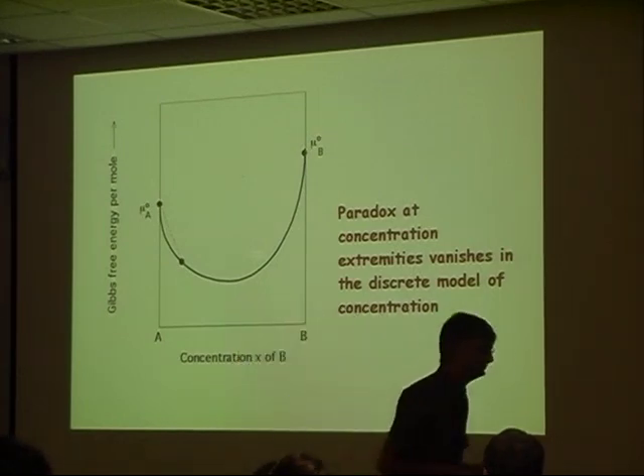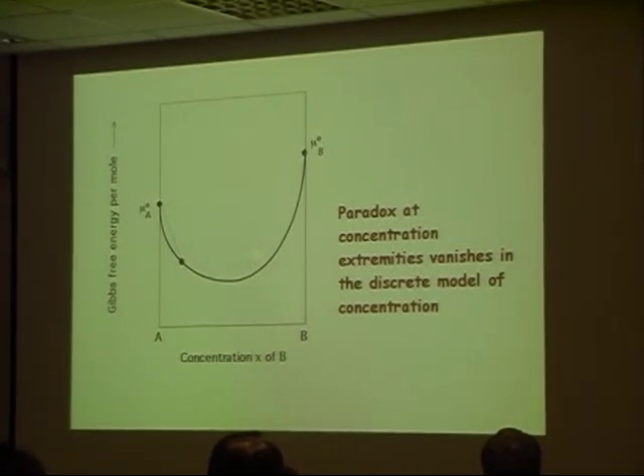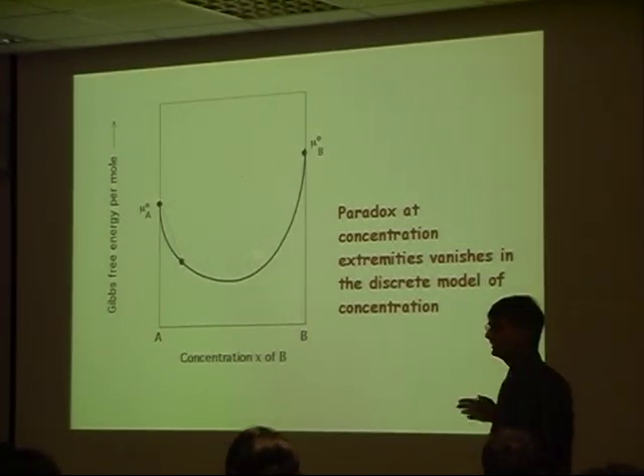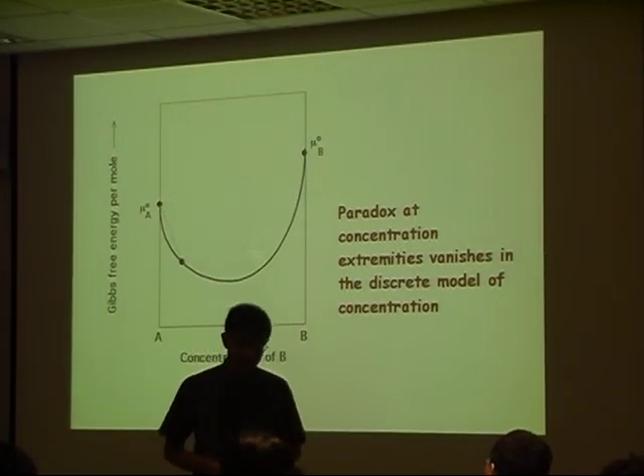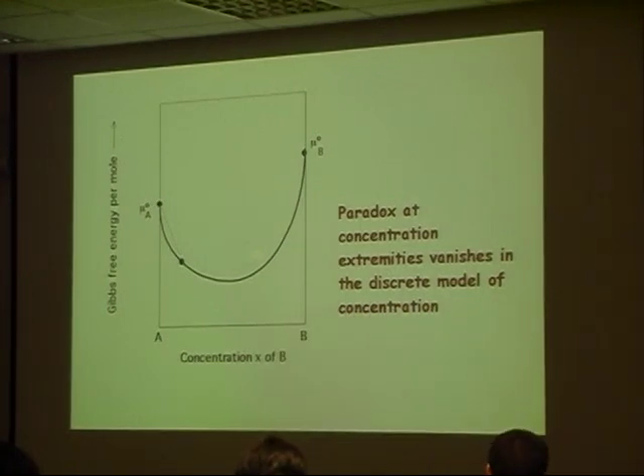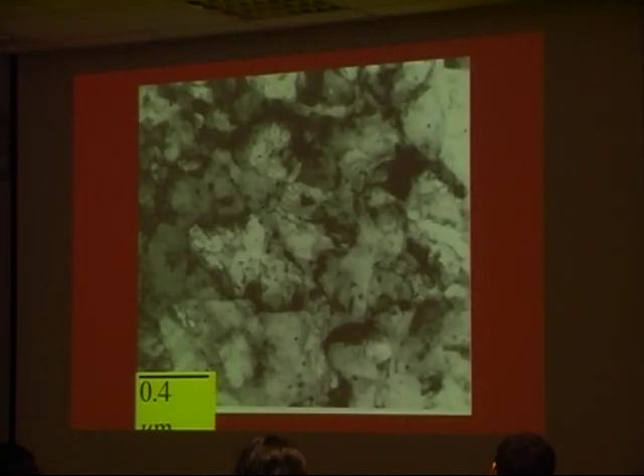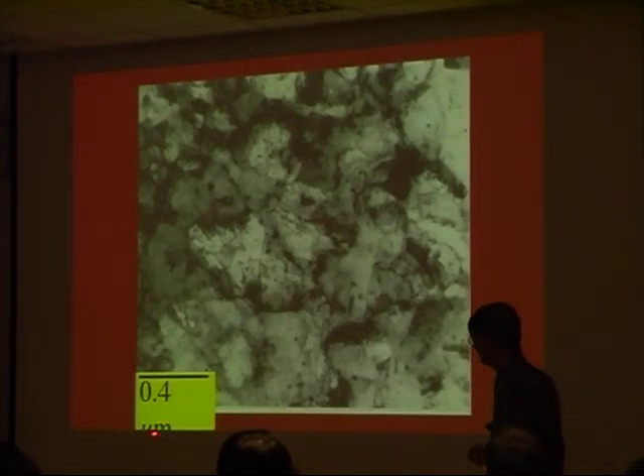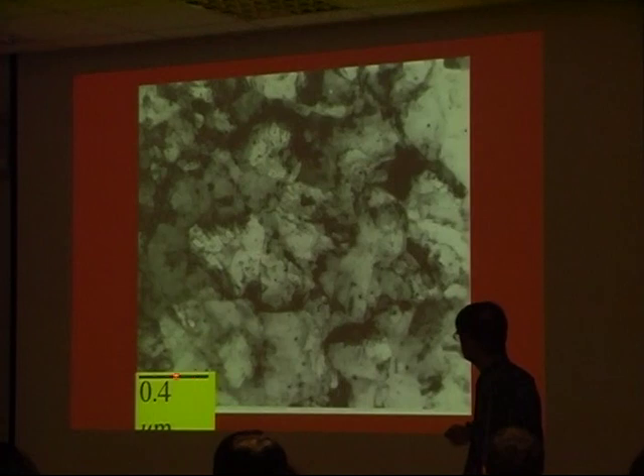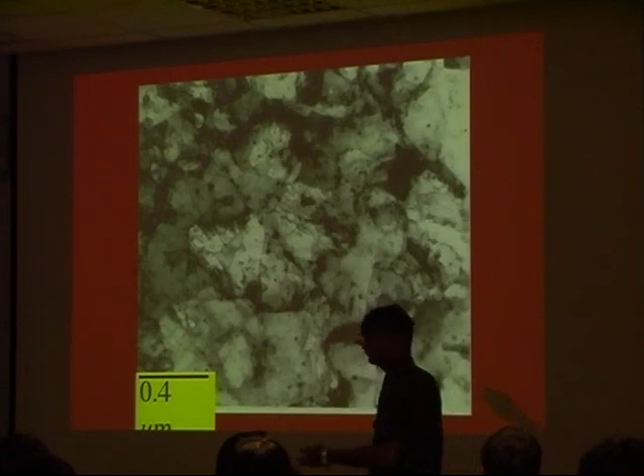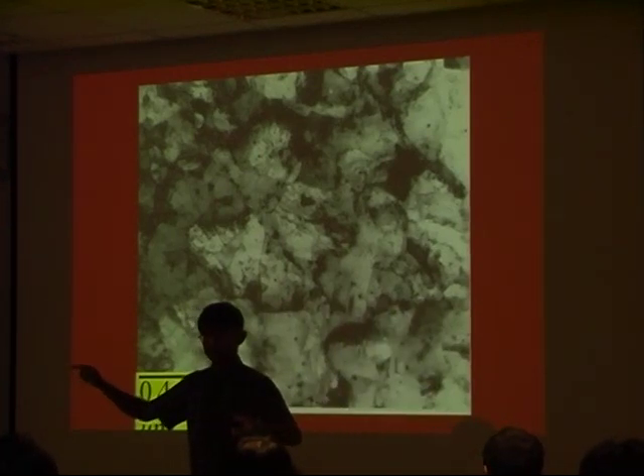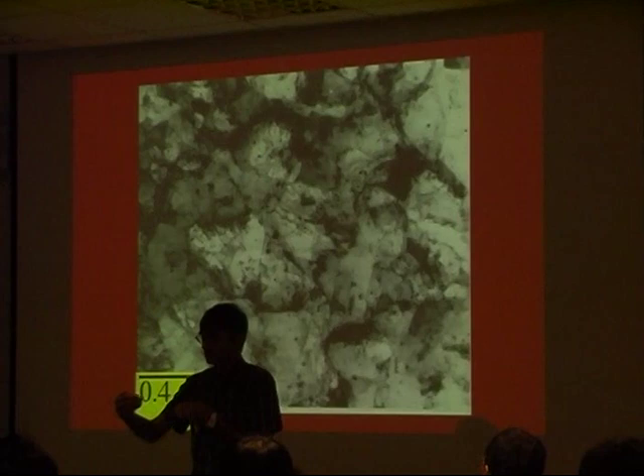This doesn't change the world as we know it, but it's very interesting that even though thermodynamics has been around for a very long time, you can still improve on it. Getting back to this point about making large quantities of cheap nanocrystalline metals, let's see how far we can go. We can produce very fine grain structures. This is 0.4 micrometers, and we produce very fine grains with a lot of misorientation between the grains. In other words, a very strong material. And this is after the powder has been consolidated by extrusion.